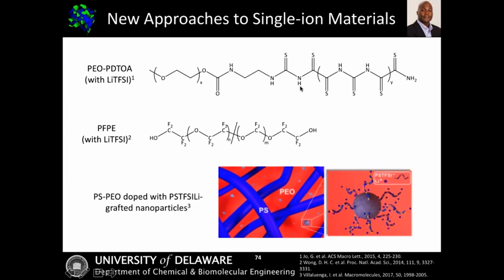But what I've done is I've actually included a polymer block that has hydrogen bonding groups that hydrogen bond with that anion. So now when I hydrogen bond with that anion, I have the lithium ion that's mobile, and I effectively have introduced a single ion conducting character to these materials. So again, this is one case where I can get transference numbers that are up above, say, about 0.7 in this particular case. And just to contrast that to PS/PEO really quick, I typically get transference numbers of about 0.2 in PS/PEO, meaning that the majority of that motion that's giving me rise to the conductivity in those cases is not the lithium.